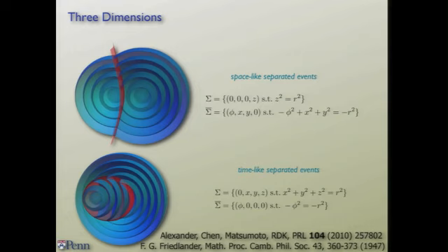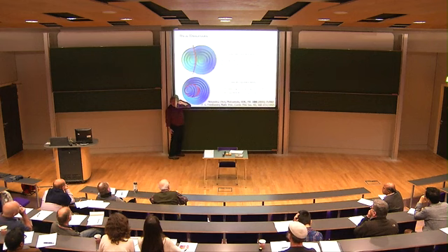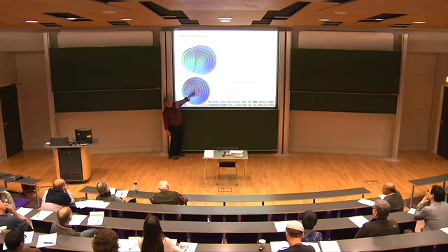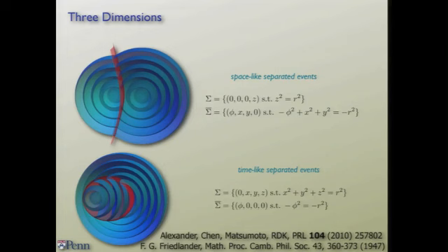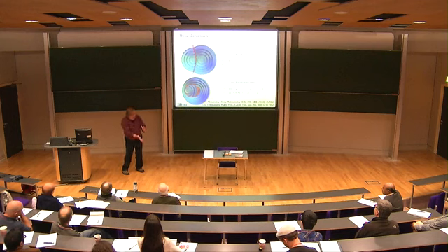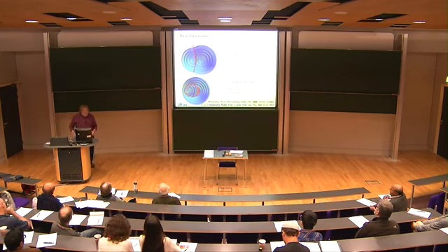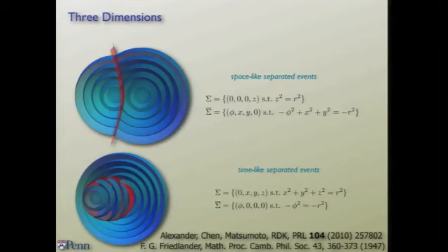Here I have concentric spheres. Here I have another set of concentric spheres. They intersect on this ellipsoid. These concentric spheres are concentric around the focus of this ellipse, and then these are concentric around those, and they intersect on ellipsoids. Or I can do the same thing in 3 dimensions. The problem is that this is energetically costly, because now I have a situation where I have a smectic, and there's this whole bad surface. There's a whole 2-dimensional surface where something's messed up. Can you fix things so that you only have 1-dimensional surfaces because they're smaller?